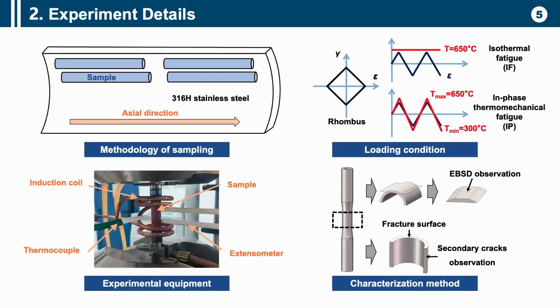In this study, the material 316H stainless steel is employed. It was developed especially for fourth generation nuclear power plants. We cut the samples from a pipe with a diameter of 800 millimeters and a thickness of 14 millimeters, with the specimen cut from the axial direction. And we designed two kinds of loading paths.